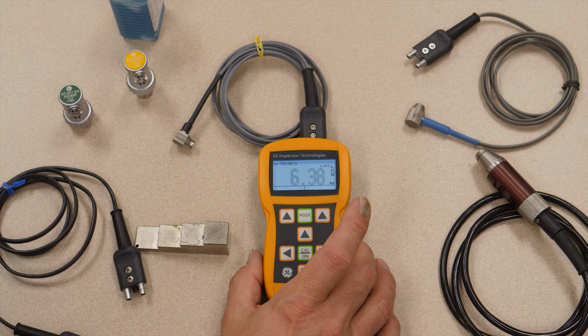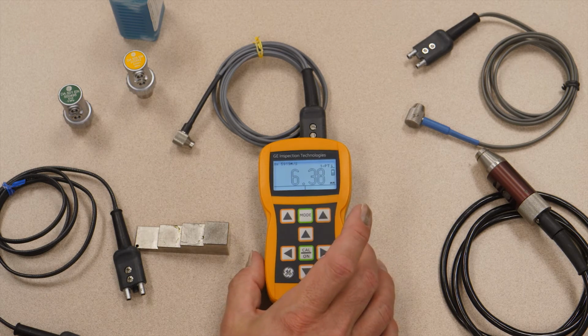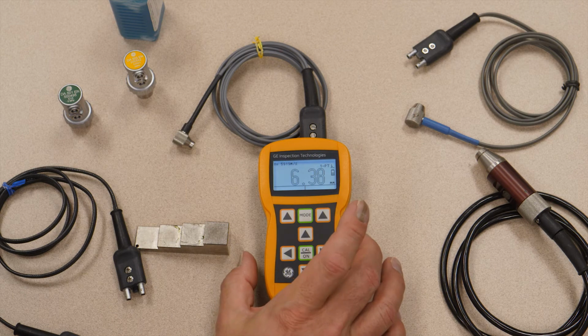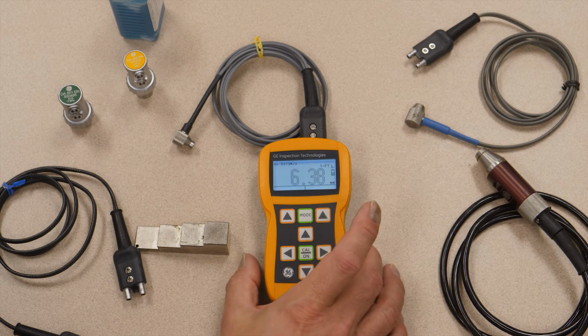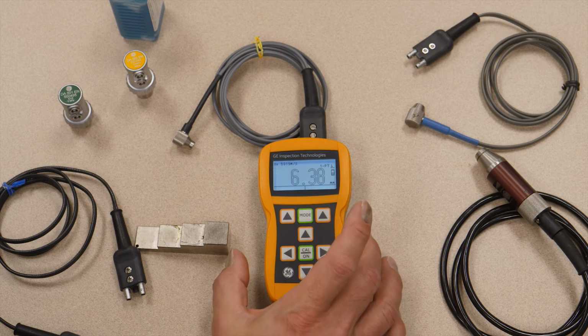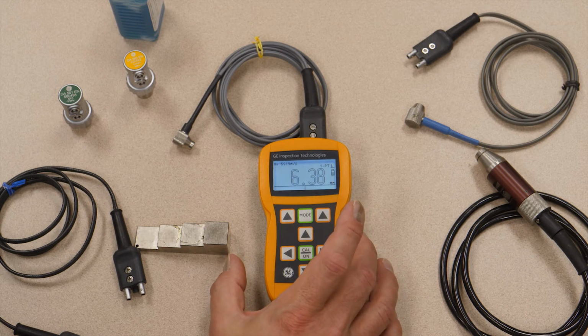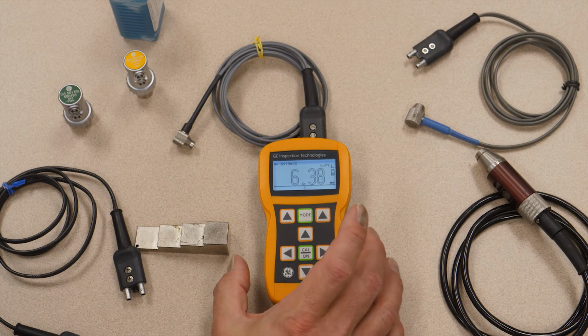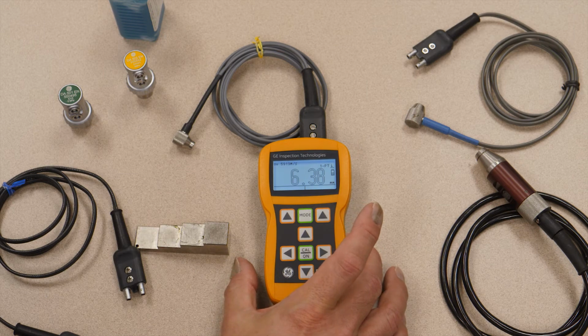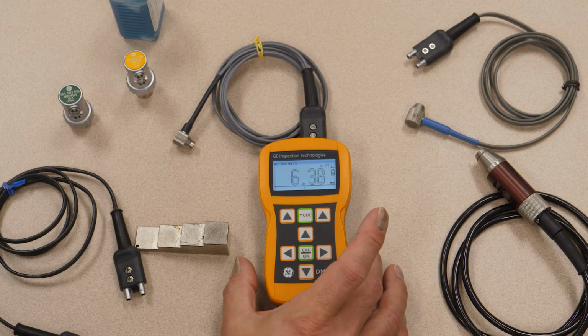The other option that's available in this instrument is dual multi-mode. And what that does is provides the capability to take measurements through coatings. So if you have painted material, if you have epoxy coatings on material, you can easily take thickness readings through those coatings. However, the coating thickness in normal dual mode will be added to the thickness of the base steel. So it's going to throw your reading off, and because the paint is typically about 1/3 of the sound velocity of steel, 10 thousandths of paint will increase your thickness measurement by about 30 thousandths of an inch.